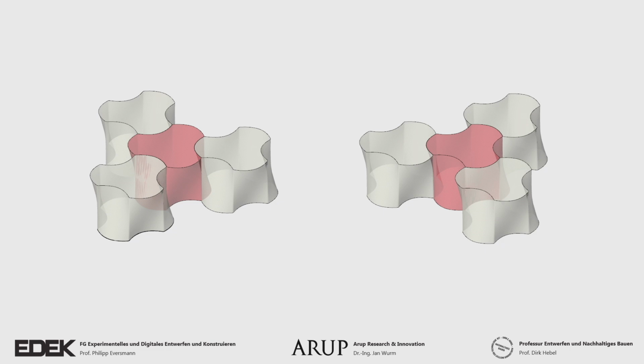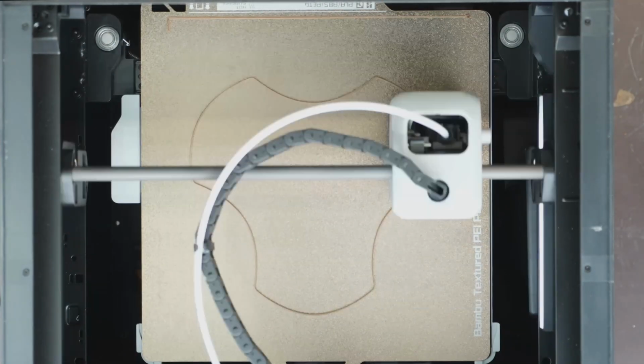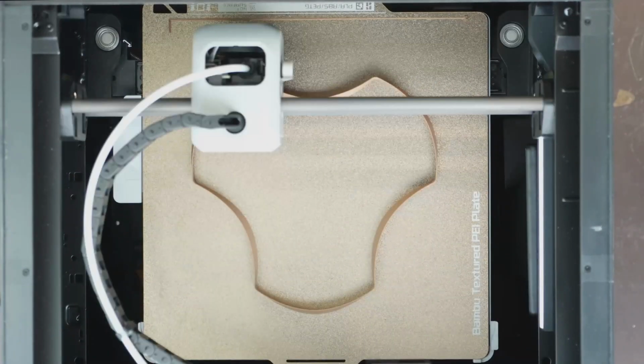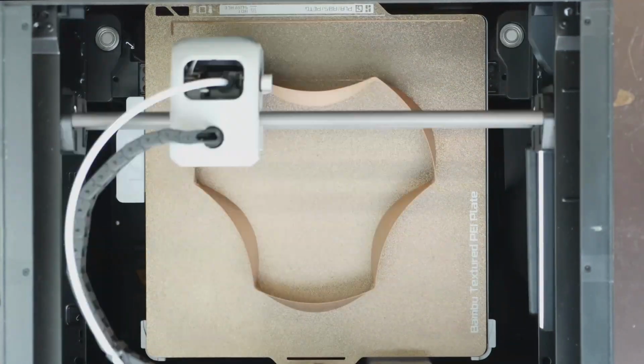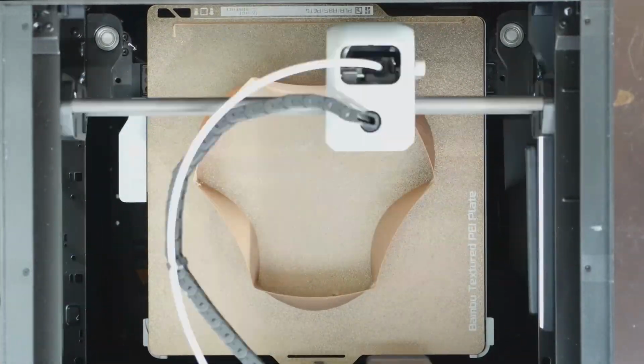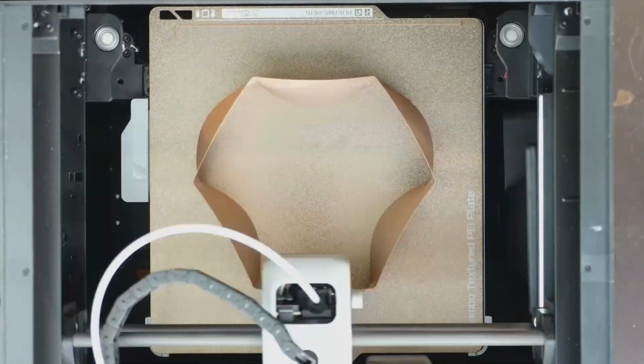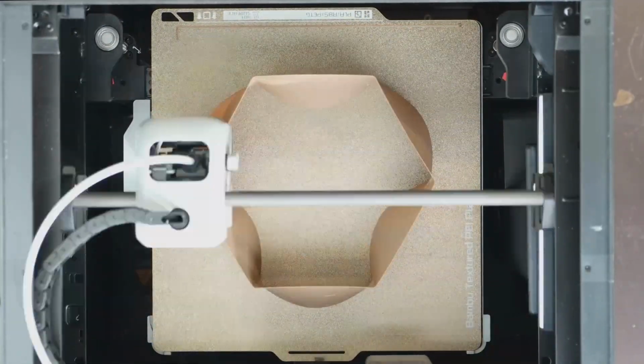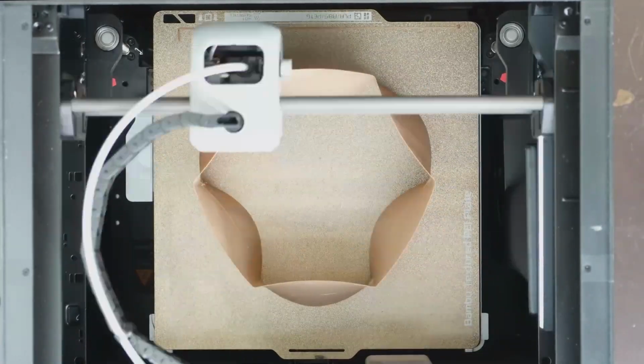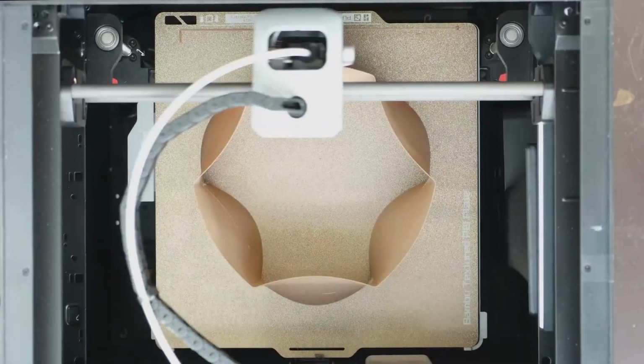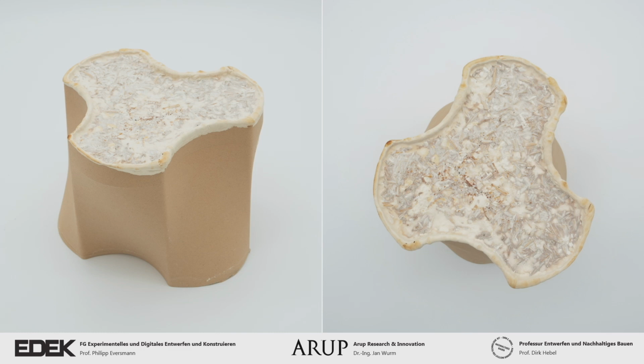However, in order to do that, we need precise interfaces. Now, mycelium is not known to be a material which has high precision. Its production process has all kinds of non-uniformities, and we have a lot of shrinkage in the material, so it's very hard to produce precise blocks. For this reason, we developed a process where we combine mycelium composites with an additive manufactured lost formwork, produced using bioplastics infused with wood particles, that we can then use to cultivate these blocks. So we end up with a mycelium composite where internally the mycelium provides the stability to the block, and on the outside we have a precise 3D printed shell that allows the blocks to properly interlock and transfer loads.